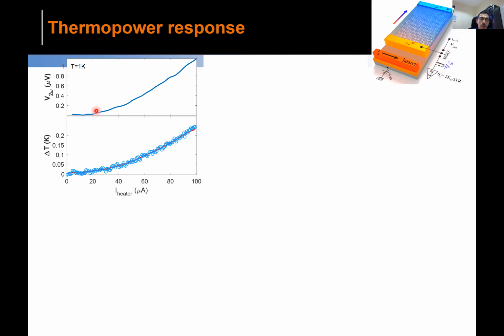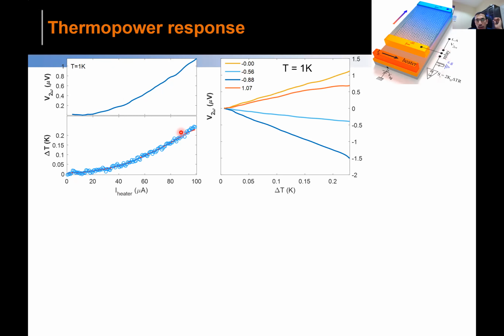So this is the thermoelectric voltage generated across the sample, and this is your temperature difference across the sample. So basically, if I plot now the thermopower as a function of temperature for different filling or different doping, they look like this. You see, they are linearly increasing, and the slope of each curve basically gives me the Seebeck coefficient for a particular filling.